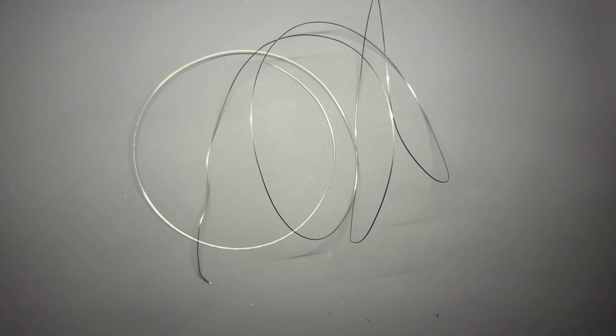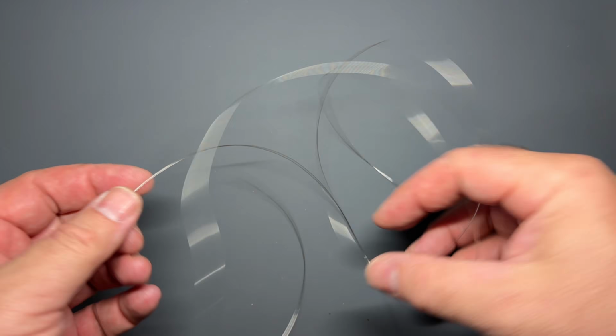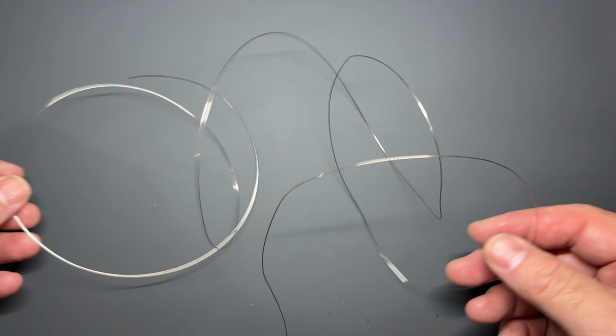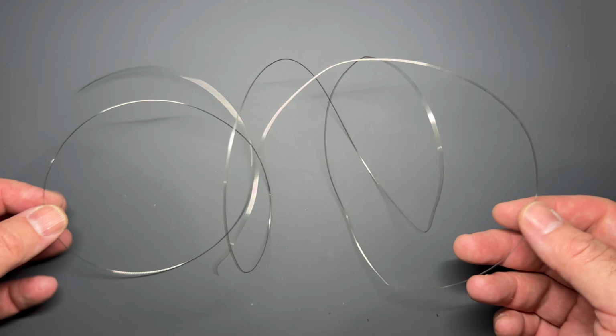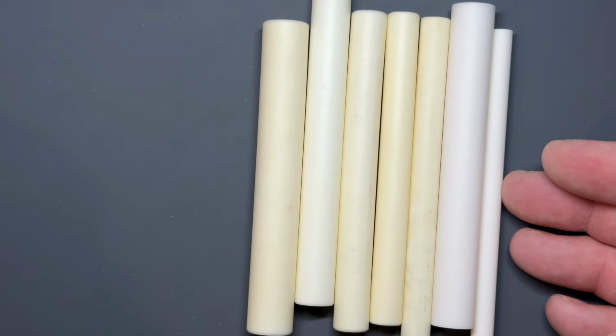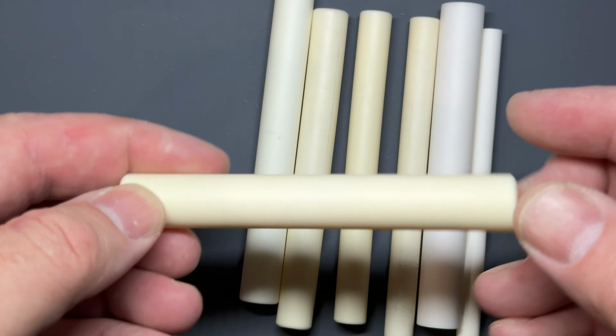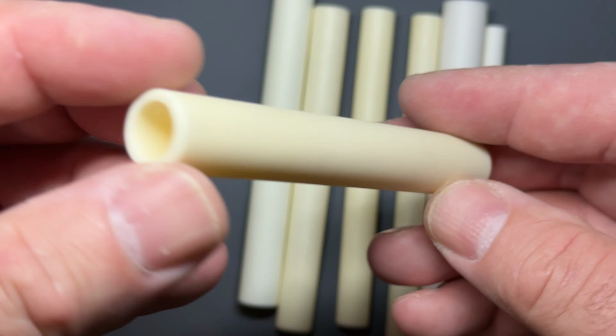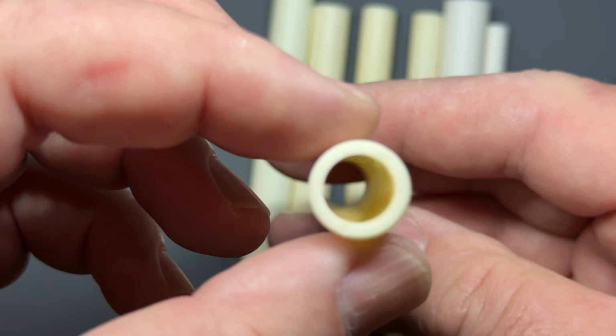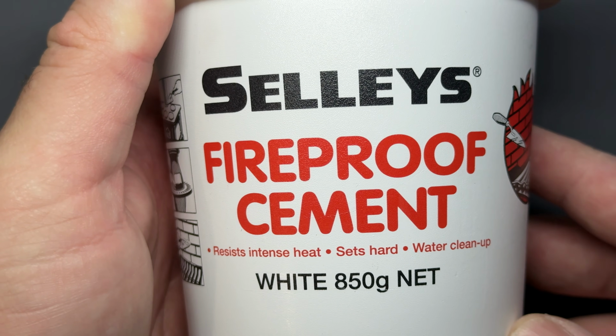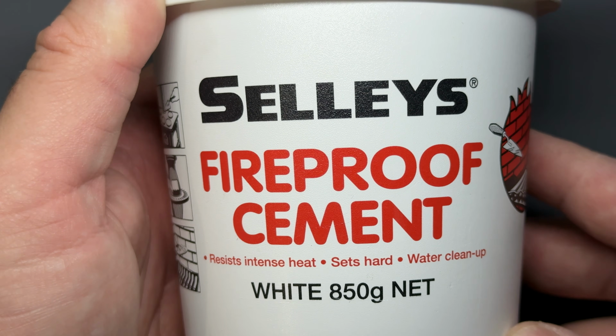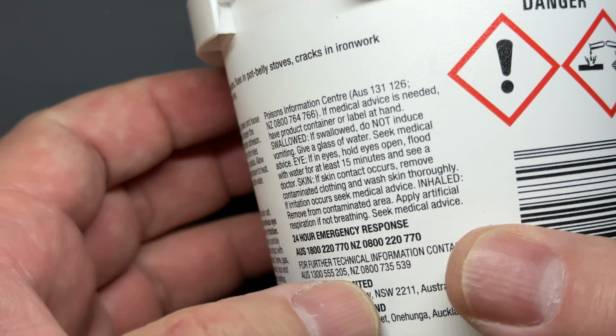For the center core that we will form the wire around, we basically need something that is electrically insulating, something that can handle sustained high temperatures, something that won't crack when subjected to thermal cycling, and something that won't conduct heat into something flammable. And for this, I'll cut to the chase. I'll be using the nichrome wire wound onto a ceramic tube. The tube acts as an electrical insulator, and it's rated for very high temperatures. That assembly, we're then going to embed in refractory cement, which is designed to tolerate heat, typically somewhere around the 1000 degrees Celsius range, without cracking or breaking down.